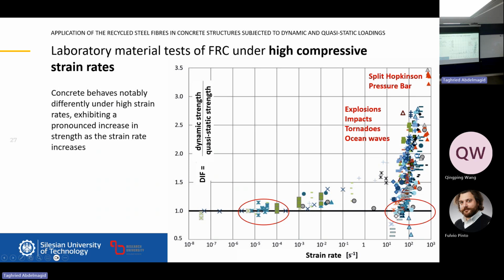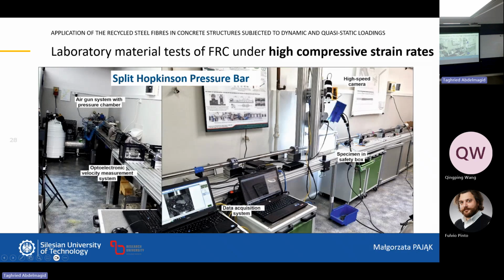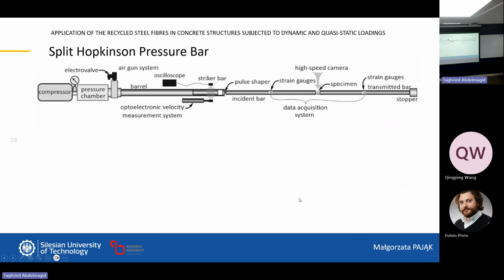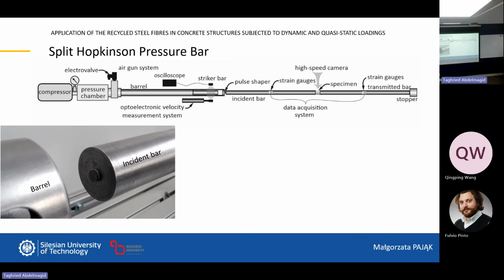And that's why the test in general is very complicated. So where am I doing this test? I'm doing this test at the Military University of Technology in Warsaw, Poland. They are equipped with the Hopkinson compression bar, and it's a very long device. It wouldn't fit here. So how does it work? We have the barrel, and here we have the striker bar that hits the incident bar, and between the incident and transmitted bar there is a specimen, and it is just crushed. However, the whole process is very complicated. We have to choose it every time for every material. Even in the same series of research, we have the concrete and we have the fiber reinforced concrete.